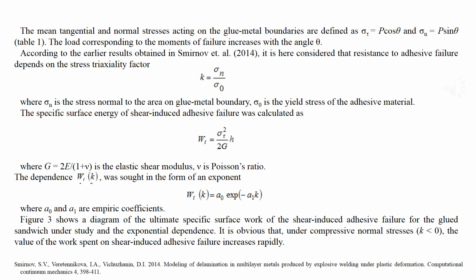According to earlier results, it is considered here that resistance to adhesive failure depends on the stress triaxiality factor, which depends on the stress normal to the area on the glue-metal boundary and the yield stress of the adhesive material. The specific surface energy of shear-induced adhesive failure was calculated as the ratio of the square of the tangential stress multiplied by thickness to the doubled elastic shear modulus.